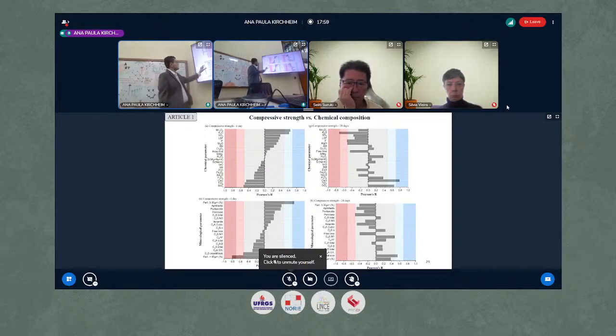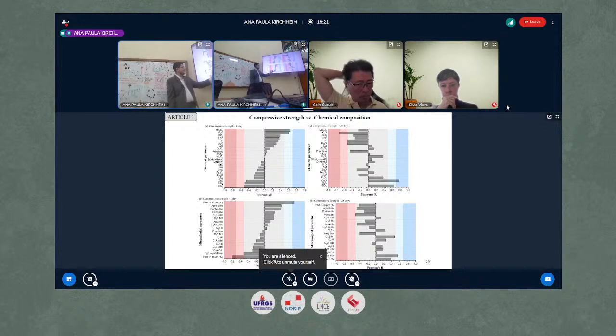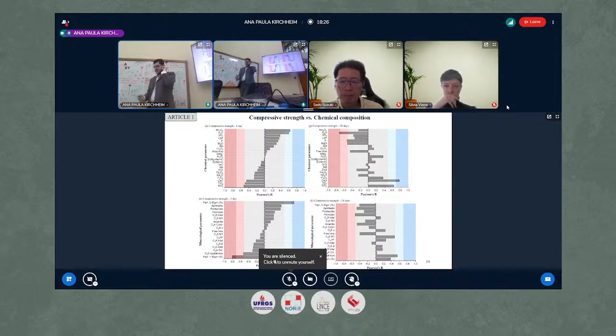And here we see the influence again of the fineness of the cement. The finer the cement, the higher the compressive strength at 1 day, and also the influence of alite crystal size, converging with the heat evolution result. So here, the alite crystal size was more important than, for instance, total C3S or total C3A content. So it's not only the bulk composition of clinker, of the main phases C3S, C2S, C3A, C4AF, that matters for reactivity.